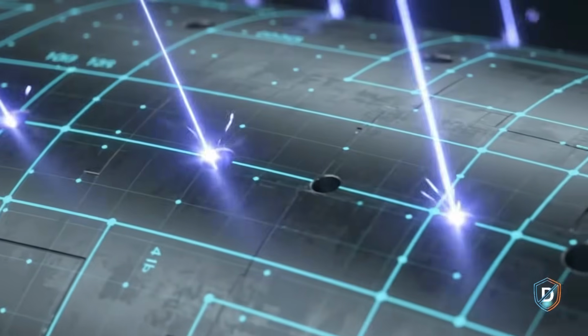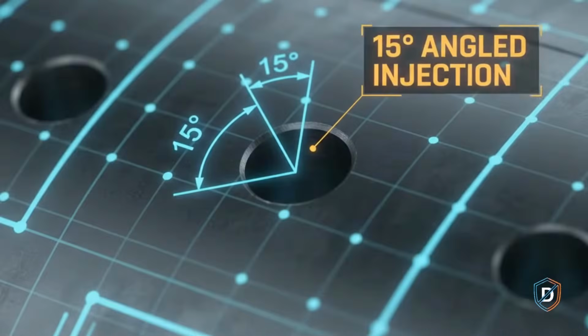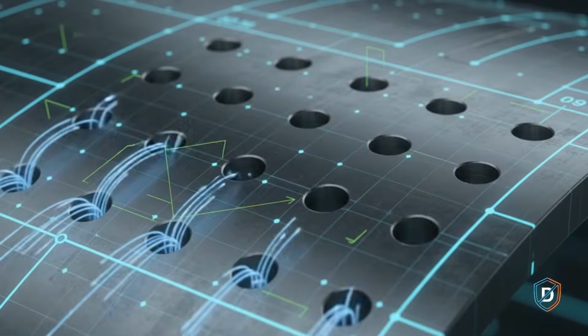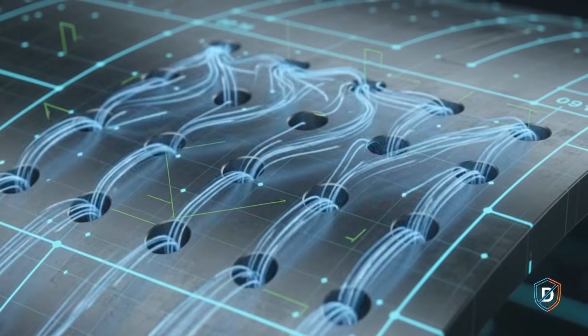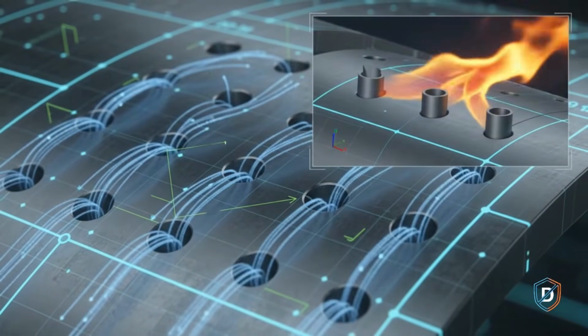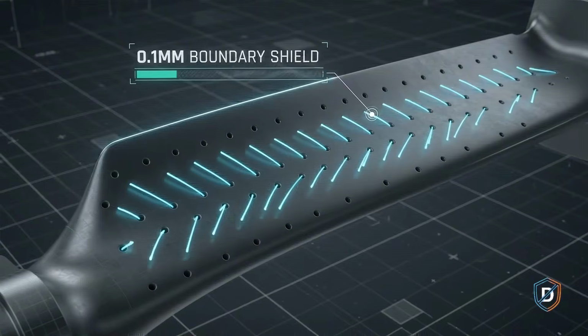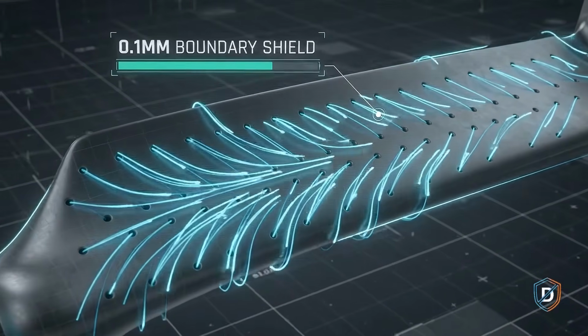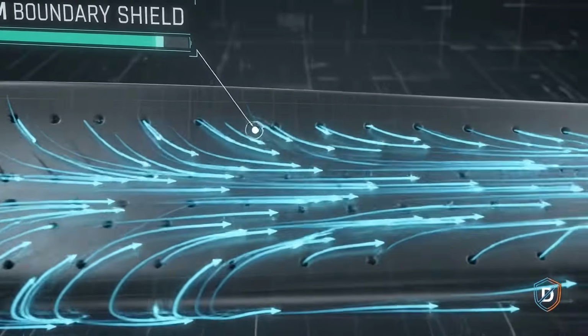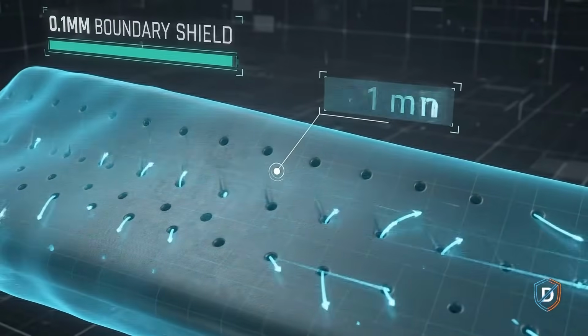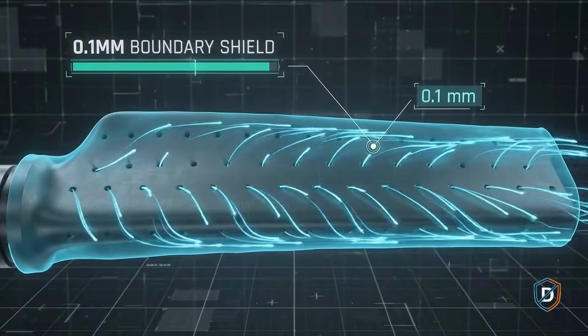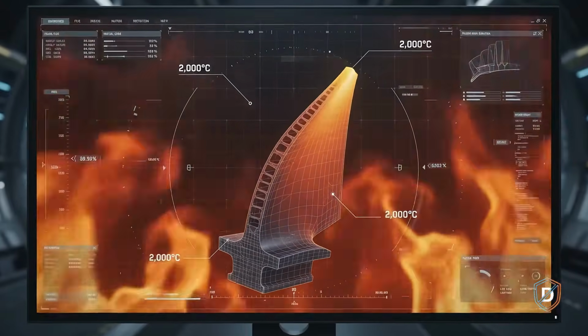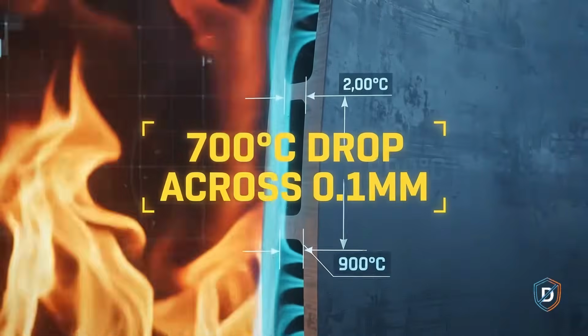To escape, the air passes through microholes drilled at precise 15-degree angles. If drilled straight at 90 degrees, the incoming fire stream would rip the cold air away instantly. This angled release creates film cooling, an invisible boundary layer of cold air just 0.1 millimeters thick that coats the blade like a fluid blanket. Across a distance thinner than a human hair, the temperature drops 700 degrees. The raw fire literally never touches the metal.